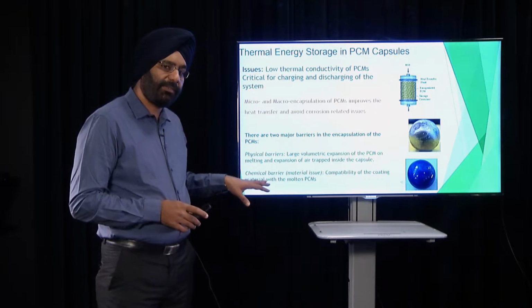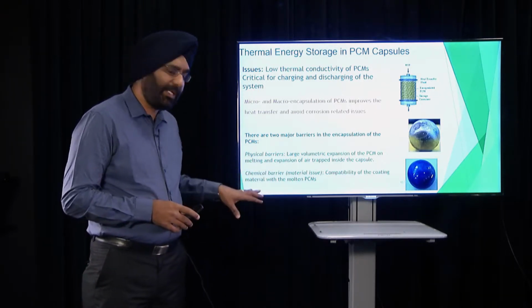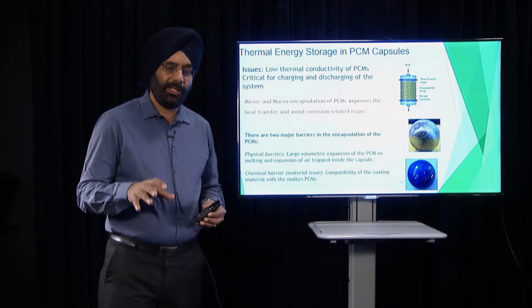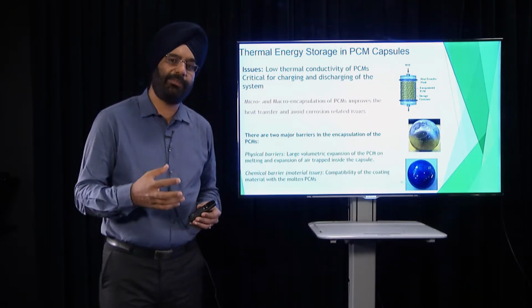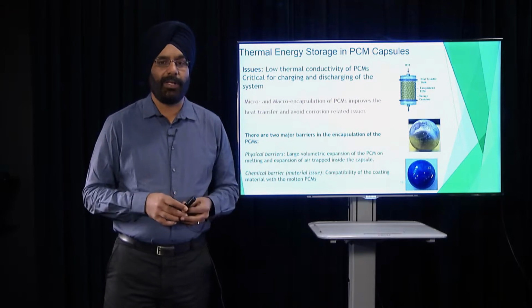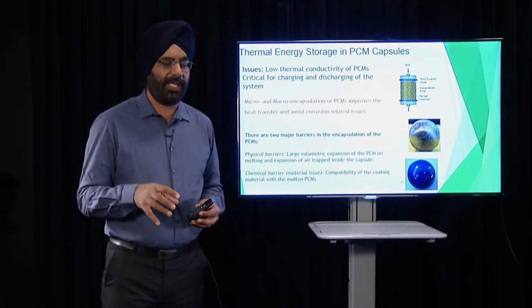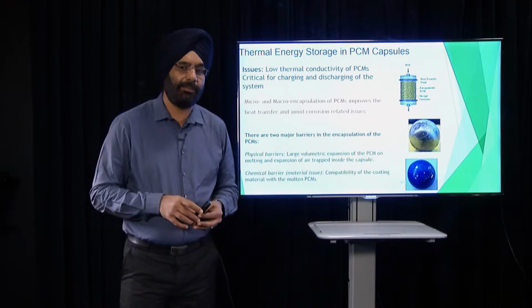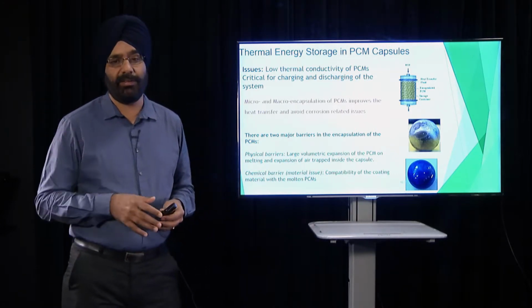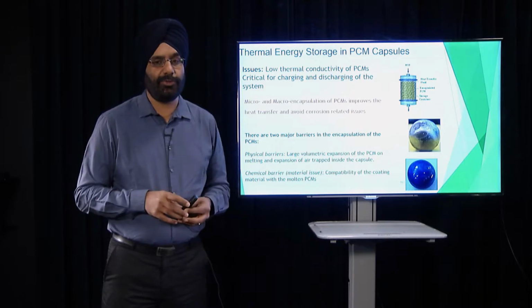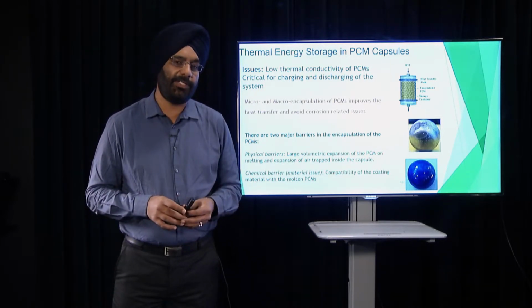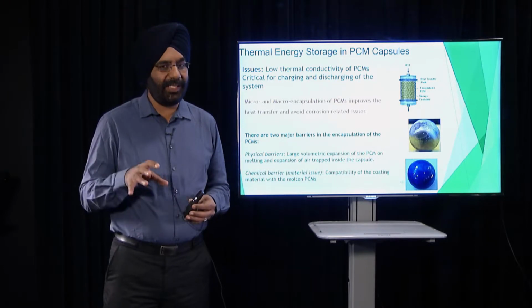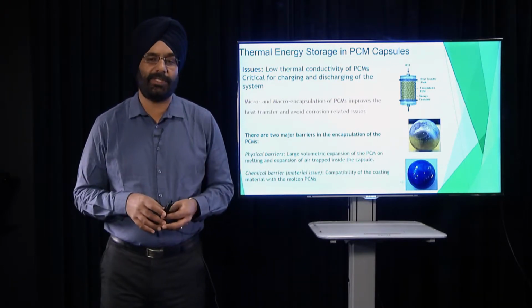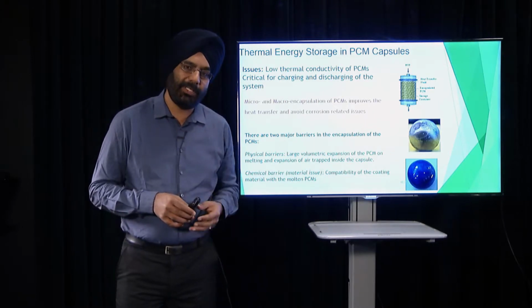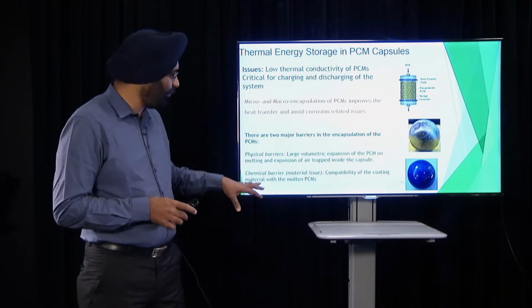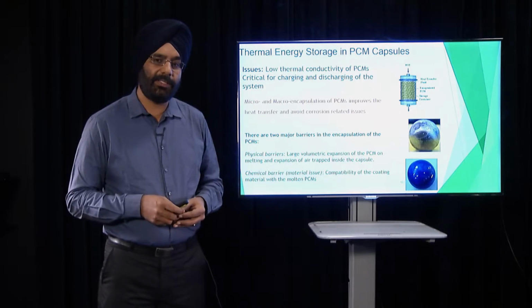The second category of barrier for successfully encapsulating is called the chemical barrier. The chemical barrier is the reaction of the phase change material with the coating. In most cases at high temperature, I'm talking about 300, 400, 500 or even 800 degrees C, the materials used to store energy as phase change materials are inorganic salts, and inorganic salts in the molten state are very corrosive. So your coating materials should not react with the molten salt.